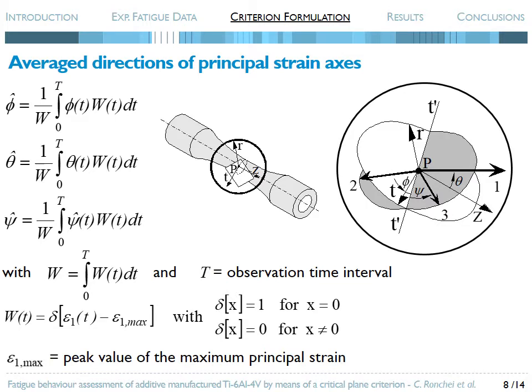According to the Carpinteri et al. Criterion, the fatigue life assessment is carried out at a verification point, P, located on the specimen's surface. Once the strain state at point P is deduced, the average directions of the principal strain axes are determined on the basis of their instantaneous directions by means of the average principal Euler angles φ^, θ^, and ψ^. By adopting the weight function W here reported, the average principal strain axes, 1^,